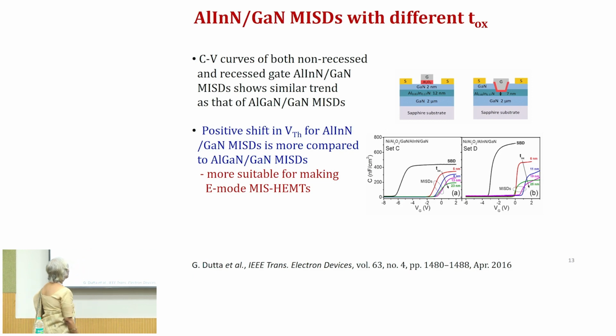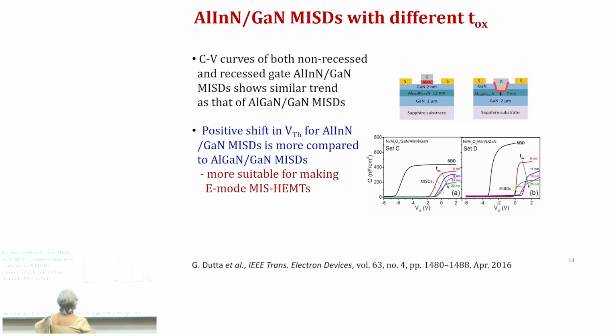What we found is that the positive shift in the threshold voltage is much better, much higher for aluminum indium nitride gallium nitride MIS diodes compared to aluminum gallium nitride diodes. That means that aluminum indium nitride gallium nitride heterostructure is probably more suitable for making enhancement mode devices. And I have here the two sets of CV characteristics showing the threshold voltage.